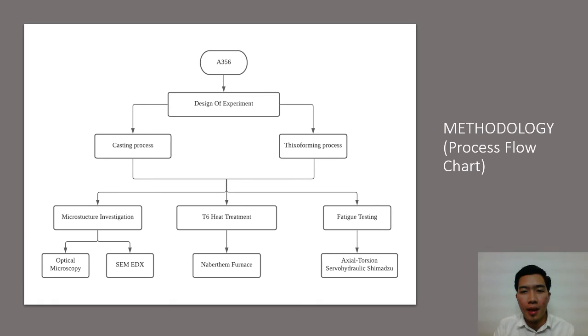So for the process flow chart, this is for the experiment that I will do. First, using A356 aluminium alloy, I start with the design of experiment. After that, I go to the casting process and the Thixoforming process. After that, I go to the microstructure investigation of the casting and Thixoforming specimens using optical microscopy and SEM EDX. Besides that, I will also do the T6 heat treatment on these specimens using a furnace. And lastly, I also use these specimens to test their fatigue properties using the axial torsion servo-hydraulic